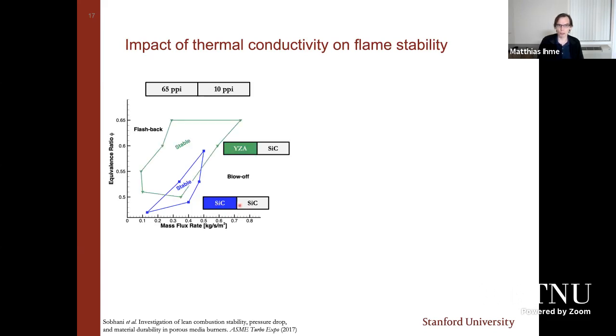And now, if we switch the material properties to YSZ in the preheat zone, remember the zirconia has a very low heat conductivity. So this essentially prevents the flame from pushing backwards. There you're seeing right away that we get a much extended flammability or stability region. And this makes it rather interesting for a number of combustion applications, right?